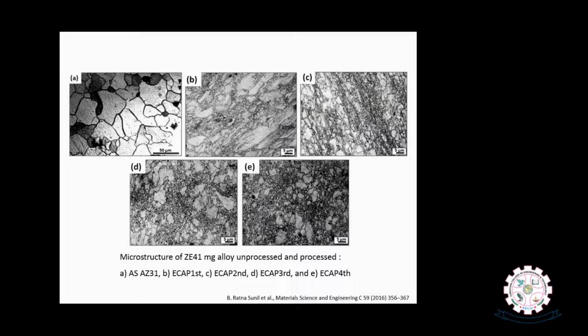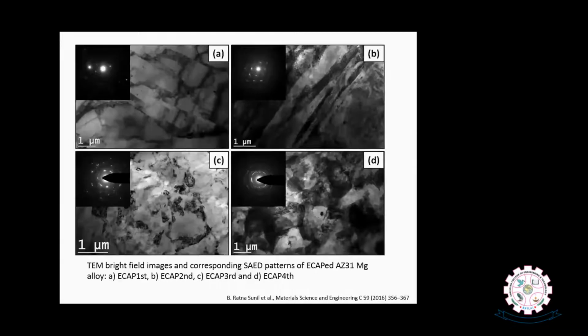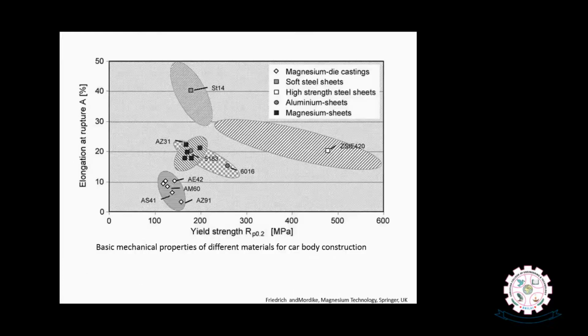However, the overall deformation was excellent, and compared with the unprocessed AZ31 magnesium alloy, we can see grain-refined small grains in the microstructure. And the corresponding TEM image also shows us the grain refinement in ECAP samples.